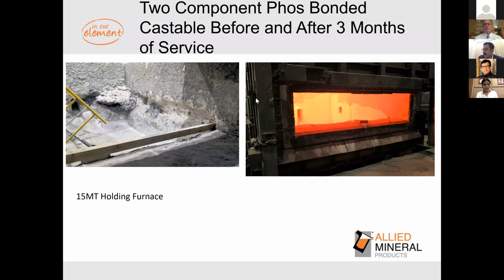This particular customer went back in with the 2-component phosphoric bonded castable, and you can see from the emissivity differences between the old and the new where they installed it. And again, after 3 months, the improvement in resistance to adherence of corundum and aluminum is fantastic. You can see how clean those areas are that have been repaired.